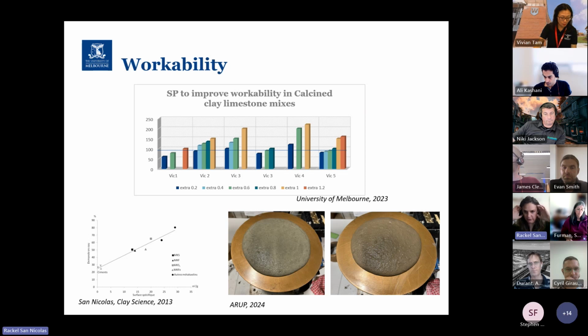So in order to have a nice flow, I've got a few pictures here with a reference with only cement and a calcined clay, where we increased by just 0.2% the amount of superplasticizer in the system in order to reach similar workability. So really, it's possible, and there are off-the-shelf superplasticizers that actually do the job.